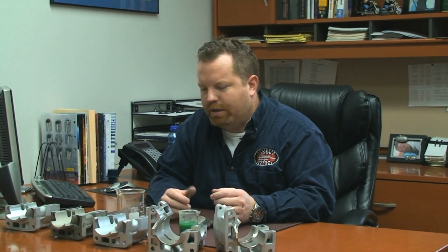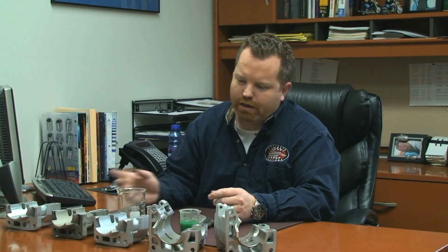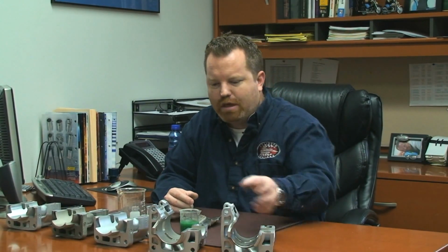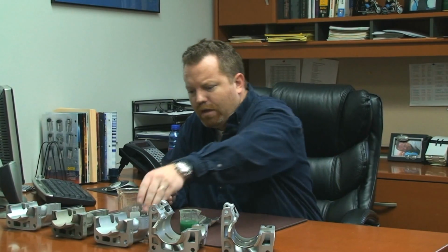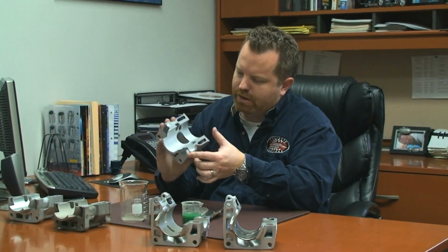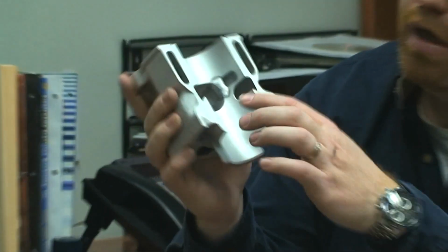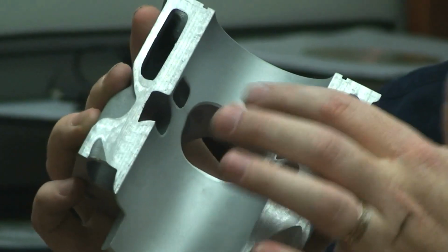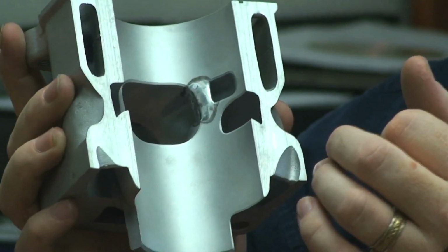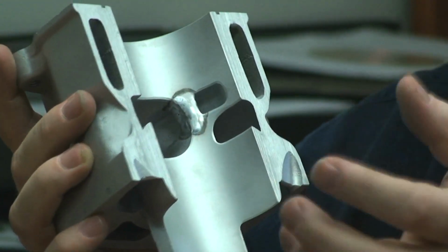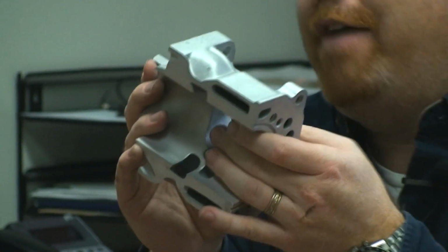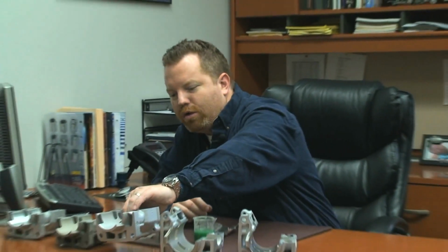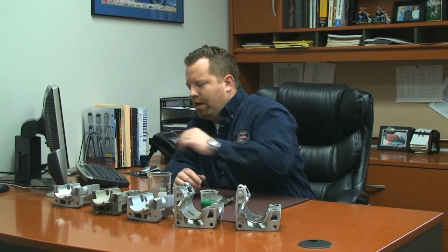The next question that we get after what is it is, how is it done? How do you actually do the process? So I'm going to show you the cylinders in a different range of steps. When we start, we get a cylinder in, and we go ahead and fix it. That's what this cylinder is here. There's some damage. It's very hard to see, but there's a crack in this triple port, and what we did is we welded it, and we move on from there. This step is after the old coating is removed and everything's cleaned.